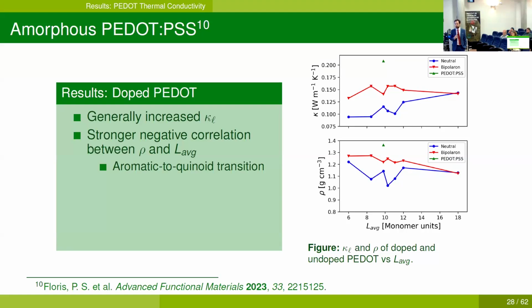We attribute this directly to the aromatic to quinoid transition. And this is because there are two competing phenomena here. So kappa L wants to increase because we are increasing the average chain length, but at the same time, the density is also decreasing. Why? Because the quinoid structure that is associated with doped PEDOT is much more stiff and rigid, and therefore it creates sort of empty spots in the sample where the interchain transport is hindered, and this is much more evident when we increase the length of the PEDOT chains. And yes, so it results in this behavior which is different from the neutral case. It's not just monotonically increasing.